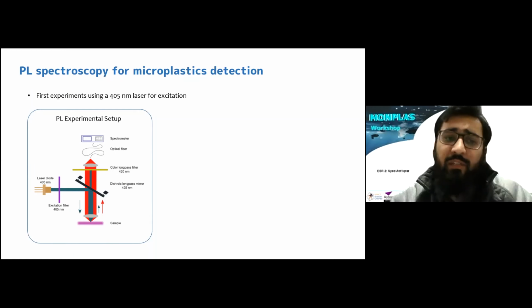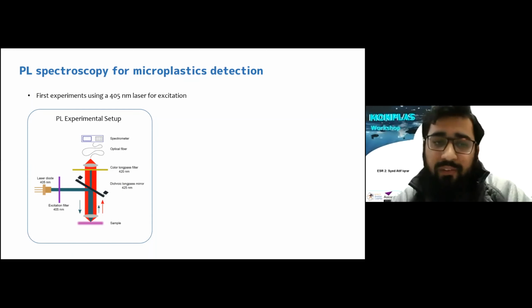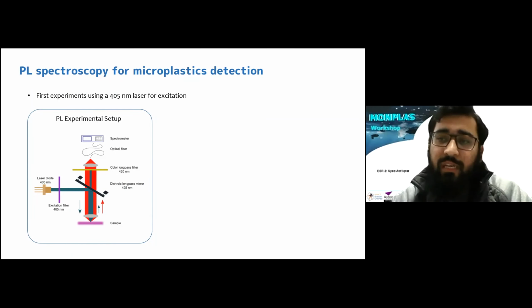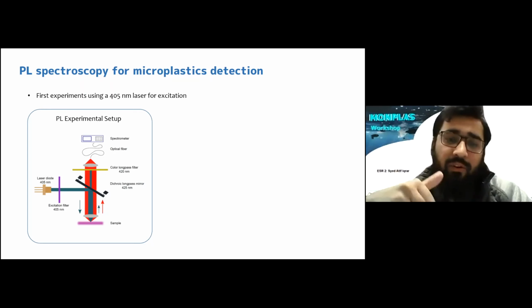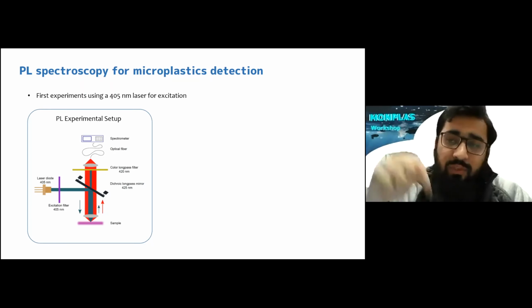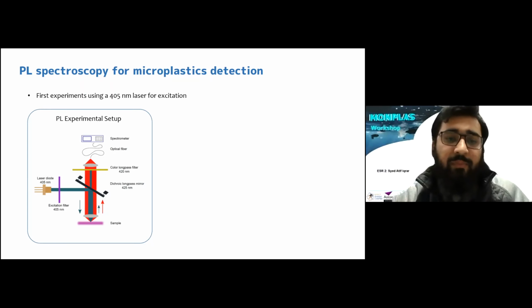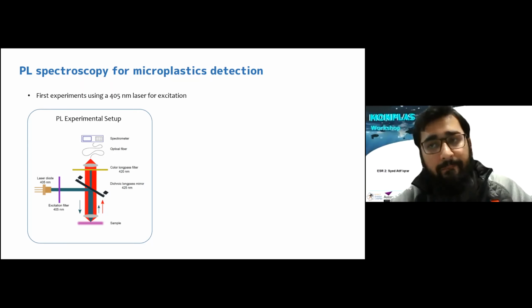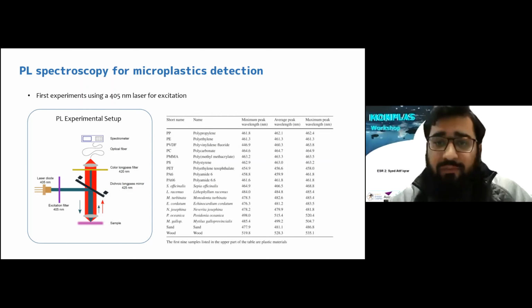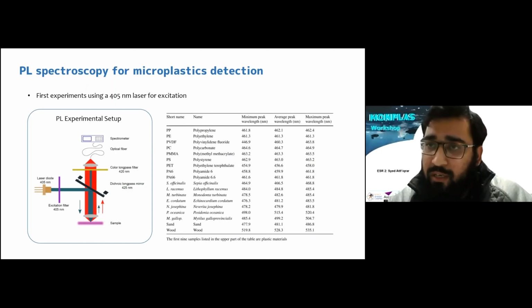You can see that they use a laser diode of 405 nanometer, and then they put an excitation filter. Then the laser light is reflected by the dichroic mirror, and then it goes to the sample. When it reflects back, we use the spectrometer to plot the emission spectra, and we see the different spectra of polymers and non-polymers.